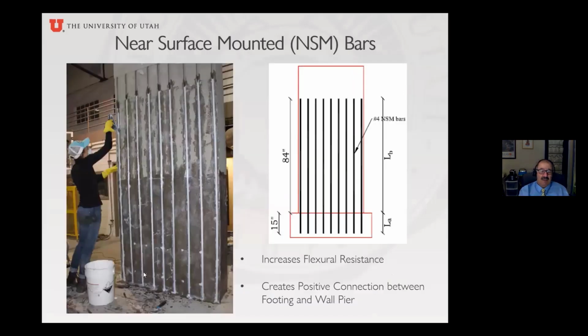Here you can see Vanessa applying the resin for those anchors. And the hard part, of course, is to drill into the footing. And that's pretty difficult, but it's difficult even with the other anchors, the splayed anchors. So yeah, it will give you a little bit of trouble trying to put it into the footing. But it does increase the flexural resistance and will create a positive connection between the footing and the wall pier.